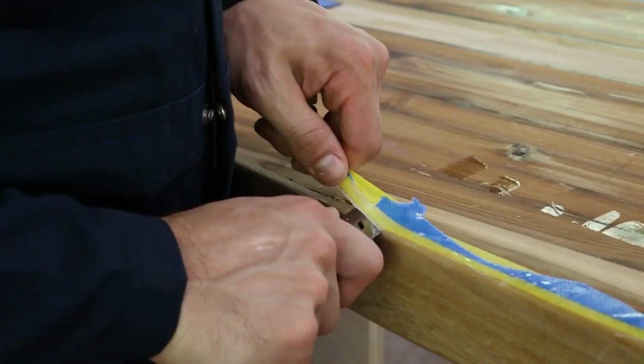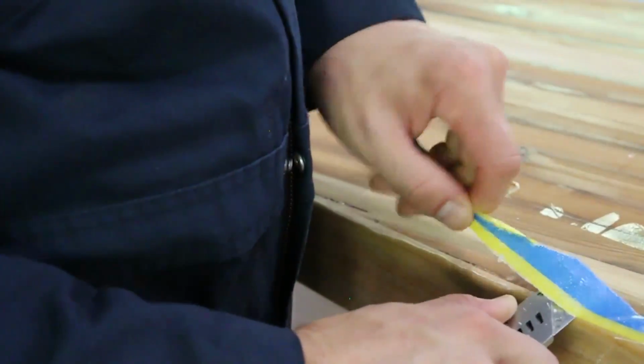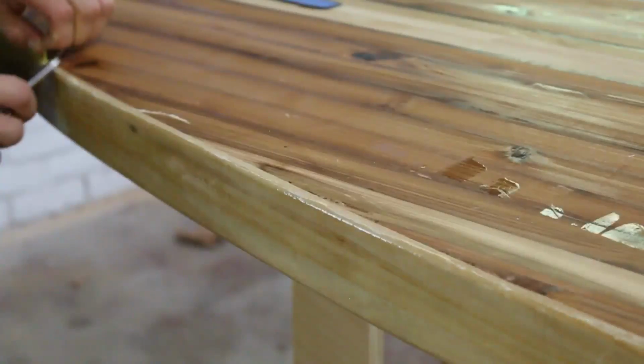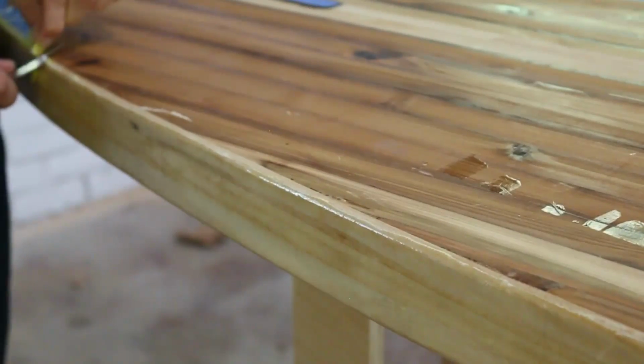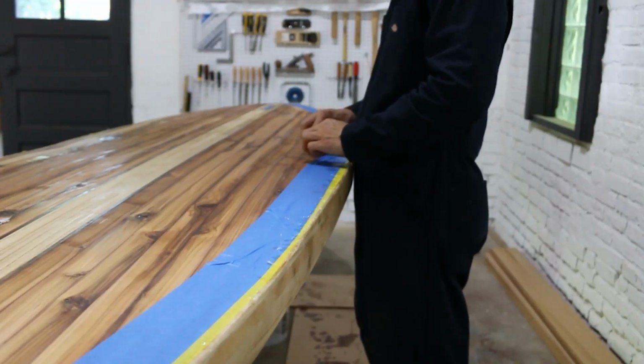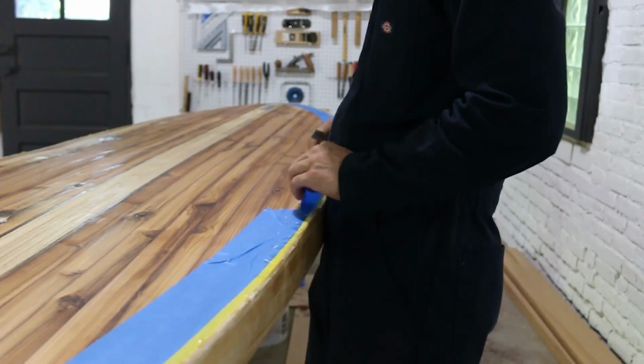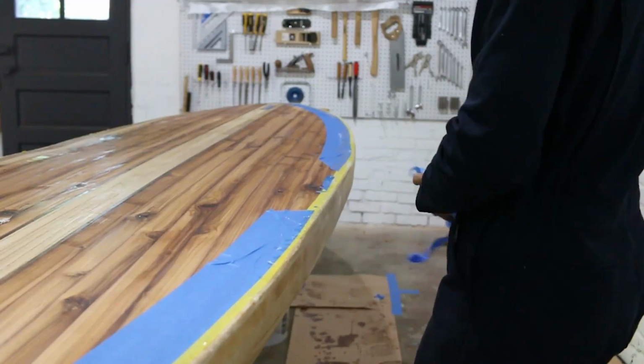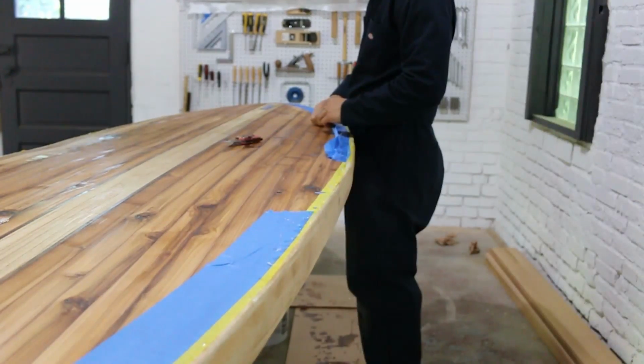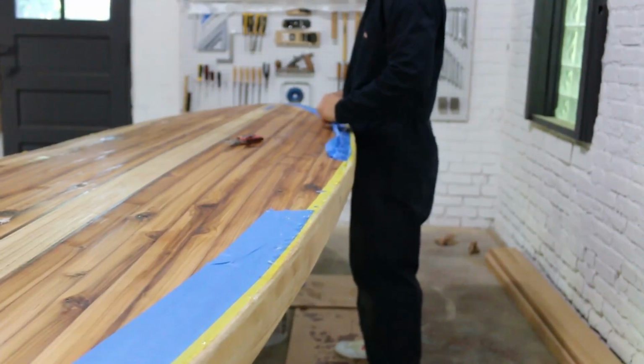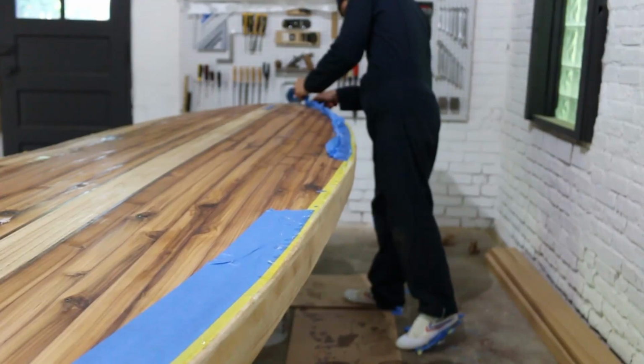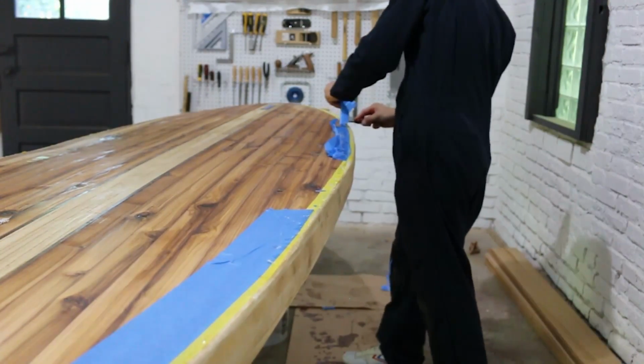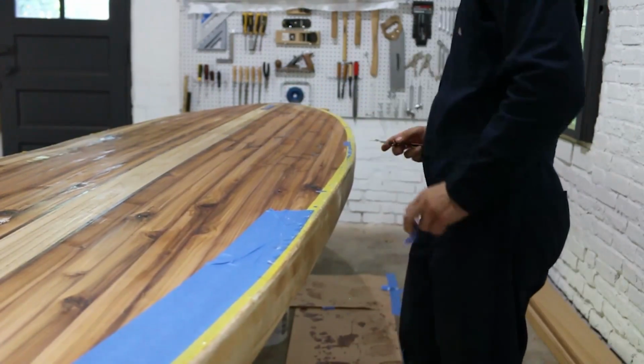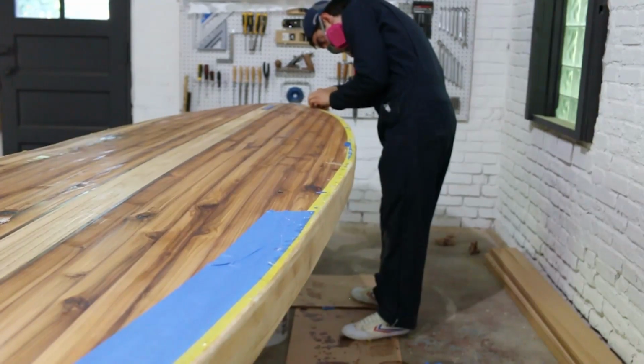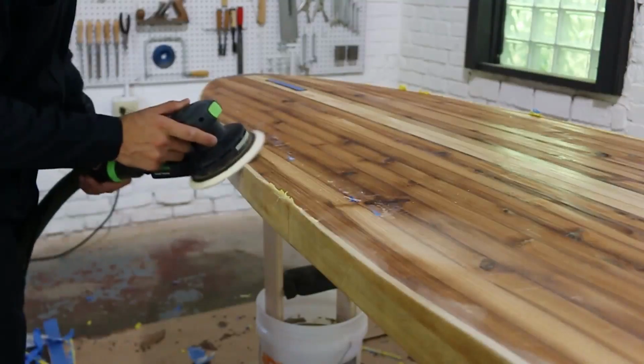To make the process of cutting this tape line easier, you'll want to wait until your epoxy is maybe 60 to 75% cured or hardened, so it should still be a little tacky and bonded to the board, but it's still a little flexible. On this top side of the board, I actually waited a little too long and accidentally let my epoxy fully cure. So when I flipped the board over and cut my tape line with a razor blade, it just took a little more extra work with my blade and some sandpaper because the epoxy was fully hardened.